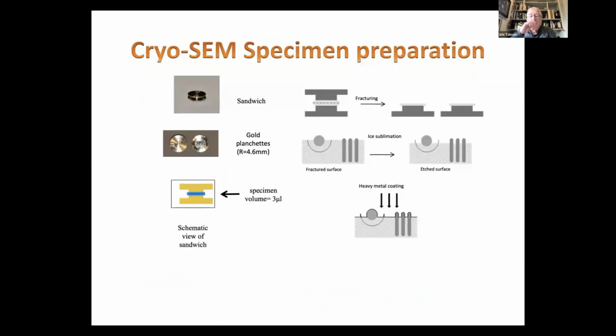First of all, how do we prepare the specimen? Typically, we use what we call the sandwich technique. We have two gold planchettes, or two gold cups, and we form a sandwich. Here you have a schematic of it, where a small volume of the liquid, sometimes a very viscous liquid, is held. We then plunge this sandwich into the cryogen. And after that, as you can see in the schematic, we open the sandwich and form the two fracture surfaces. And these are the surfaces that we are going to examine in the microscope.